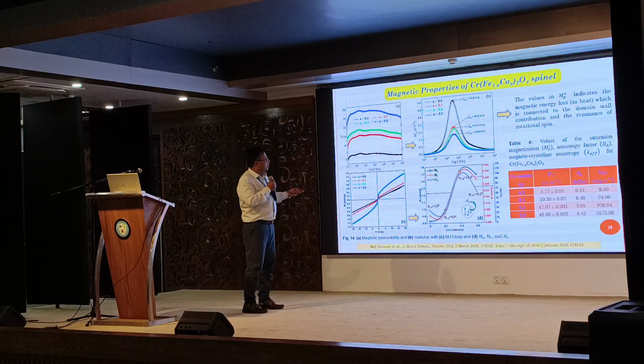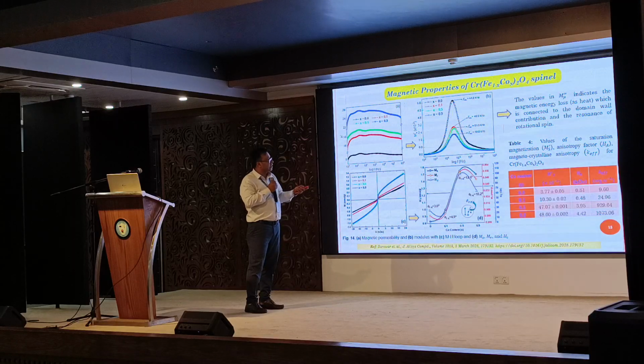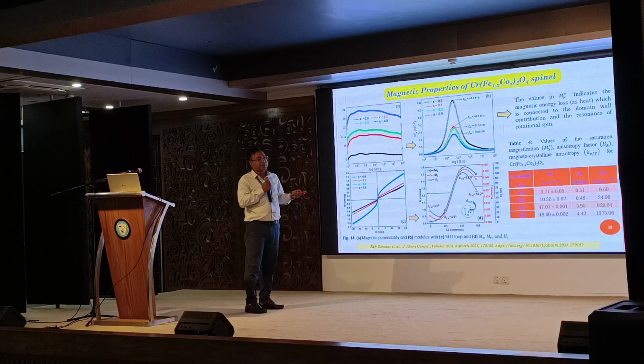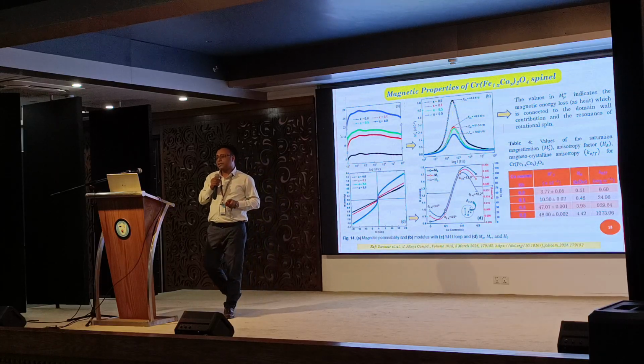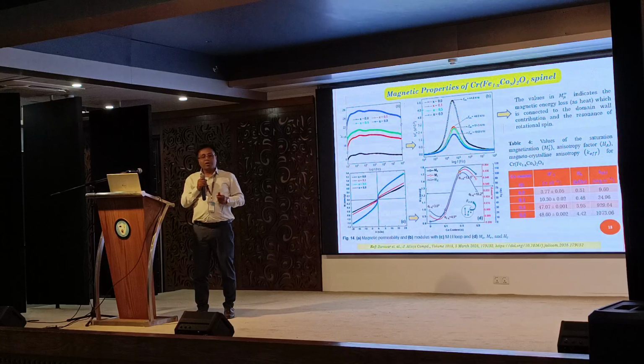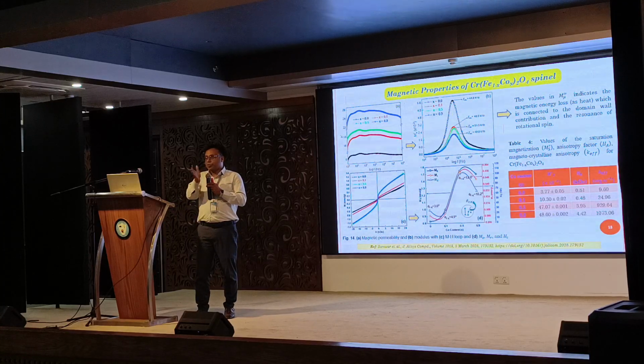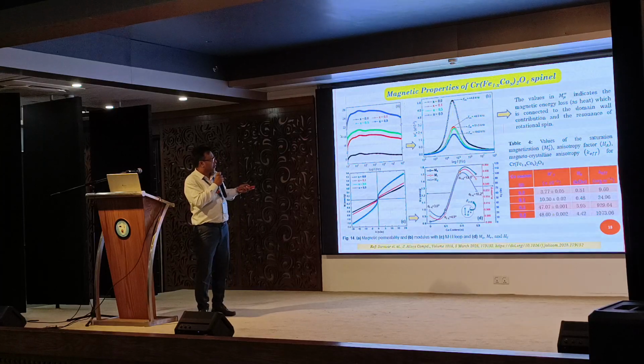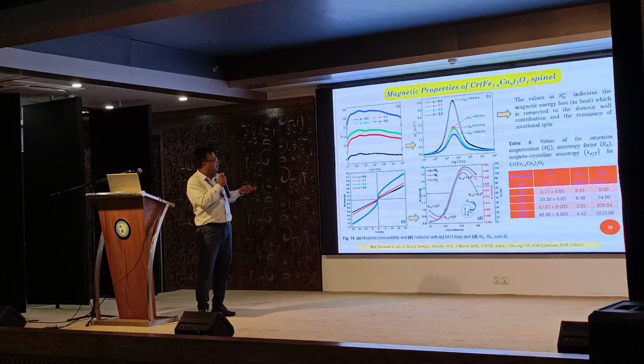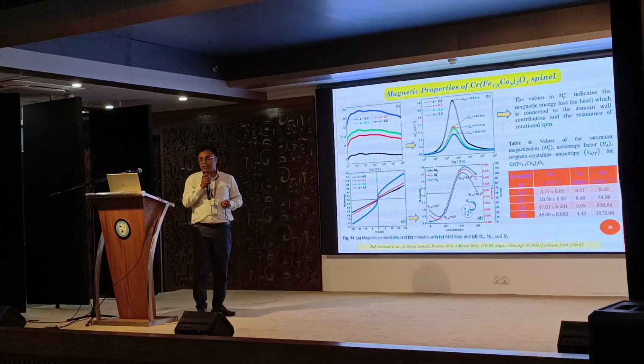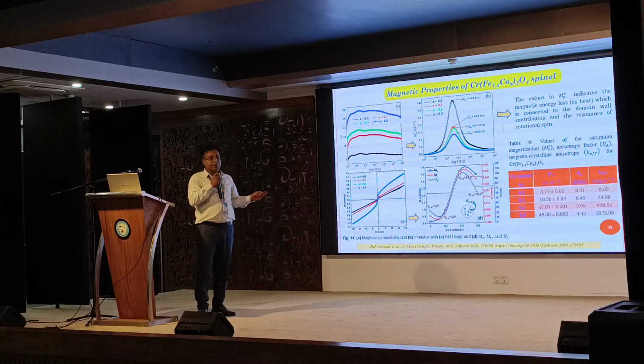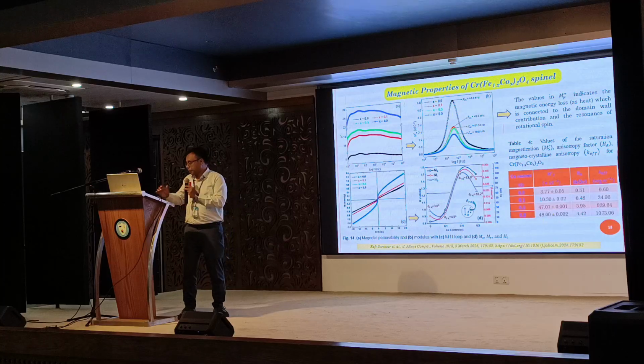And here it is showing the loss factor, the amount of loss. Here it is written that it indicates the magnetic energy loss as heat. This also indicates that whenever we apply a magnetic field inside the material, it will generate some heat because of dipole magnetic domain polarization. It will show some rotation of spin, resonance of the rotation, and this frequency confirms that if we apply an AC magnetic field of around 48 kilohertz or 51.5 kilohertz, it will generate some heat, like induction. These materials can generate some heat. So this is my core finding.